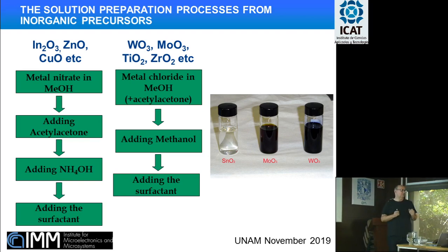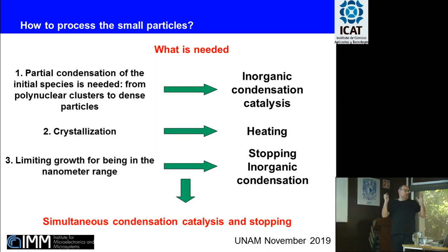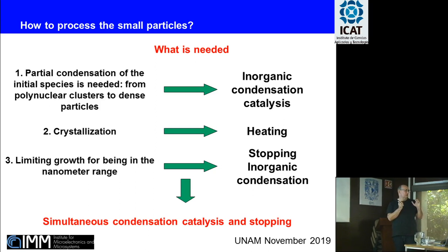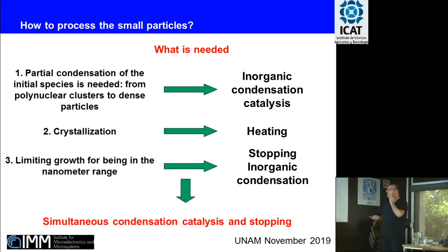And then, how to go from these small particles to the nanocrystals. We need to condense these small particles in some way, because they are some kind of inorganic nanoclusters with a few atoms. I don't really know the exact structure of these nanoclusters. Then we have to provide some heating for having crystallization. But also, at the same time, we have to make sure in some way that these particles do not grow too much. At a certain point, the growth must stop, so we remain in the nanocrystalline regime. Otherwise, we have an enormous precipitate and we have not solved anything. So how to do this?